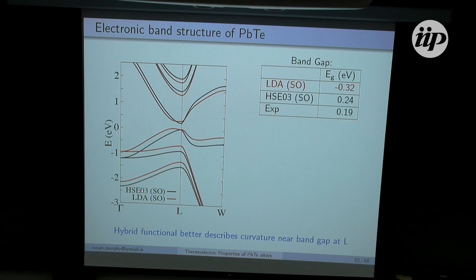In this case, I've just chosen HSE03. Focusing in on the band gap, we see the curvature of the bands looks a lot more reasonable in this hybrid functional compared to the case of LDA. Measuring the value for the band gap, LDA had about minus 0.32, but the hybrid functional captures a very good value of about 0.24, compared to the experiment at 4 Kelvin of about 0.19 eV.